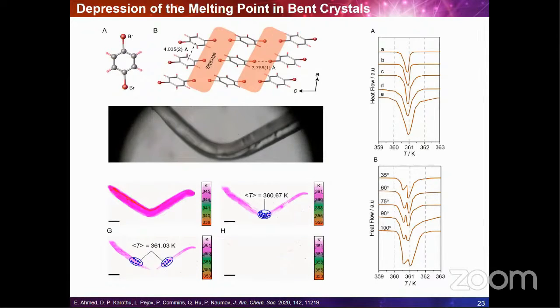Both our group and also other groups have observed that with the plastically bent crystals, there is a small and yet significant decrease in the melting point of about 0.3 to 0.4 Kelvin. So the bent section of the crystal was found to be mechanically softer relative to the straight sections, and this softening temperature preceding the melting was also lower on the convex side of the bent crystal. So melting of the bent crystal starts at the kink of the crystal and often appears as a splitting of endothermic peaks in the DSC fingerprint, while unilateral compression of the crystal results in multiple peaks.